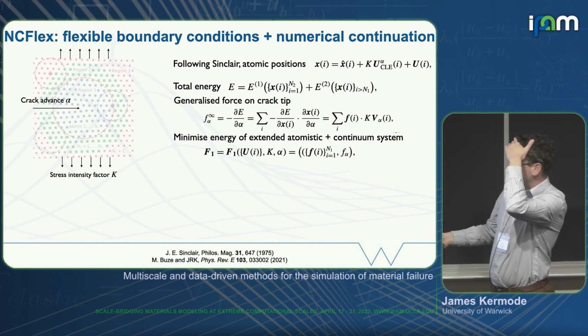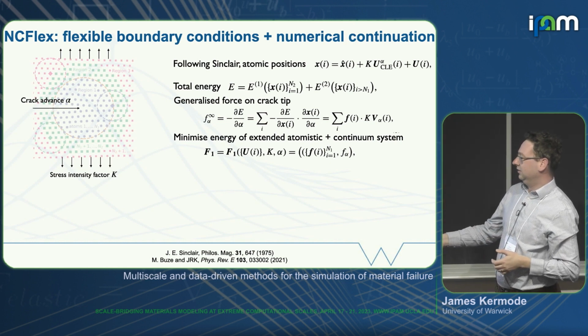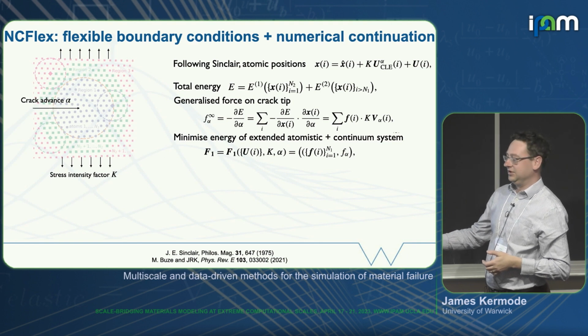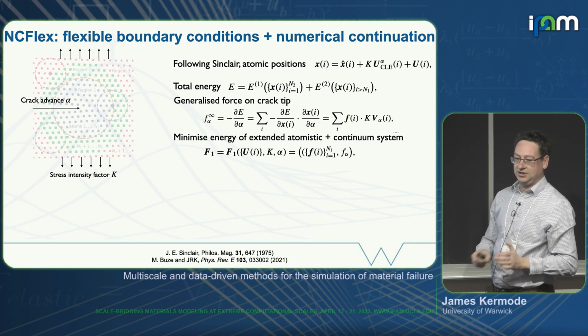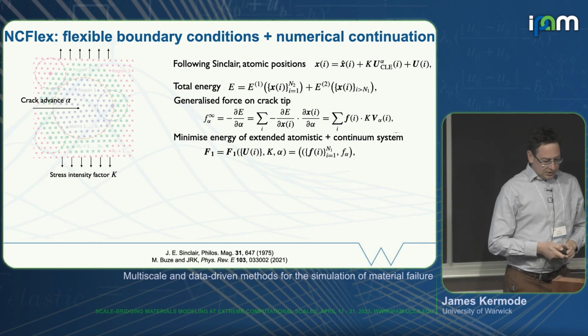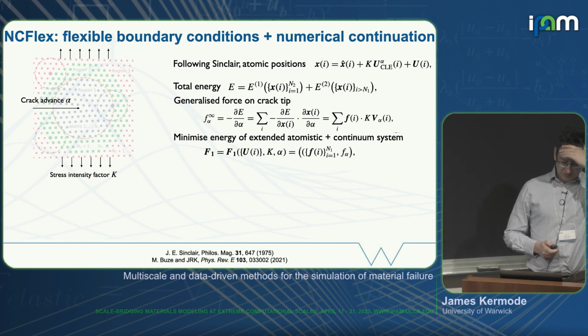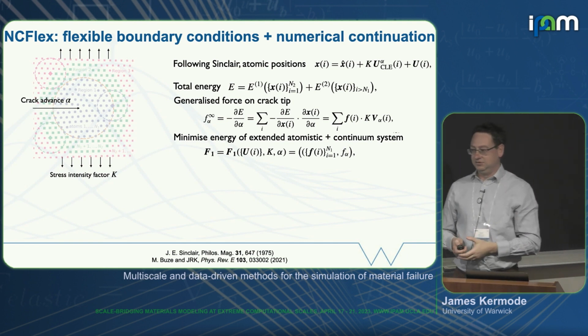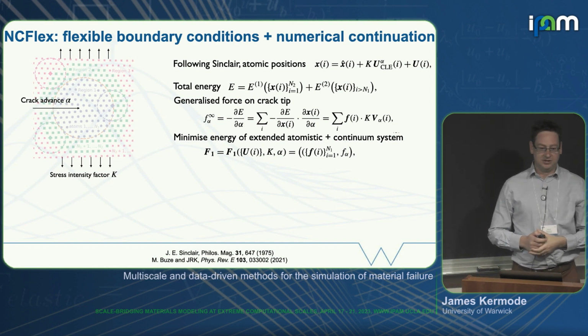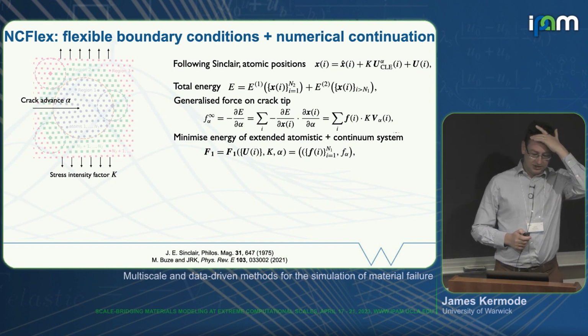We have forces on atoms that we can use to drive the internal degrees of freedom on the atomic part of the system, and then we have this generalized force that drives the crack tip. Okay, so that was the method as originally proposed by Sinclair. It's been extended and used in other contexts, particularly for dislocations by Dallas Trinkle and others.